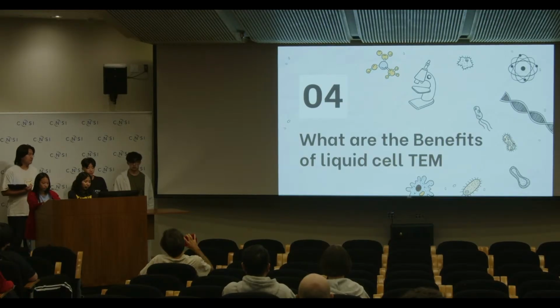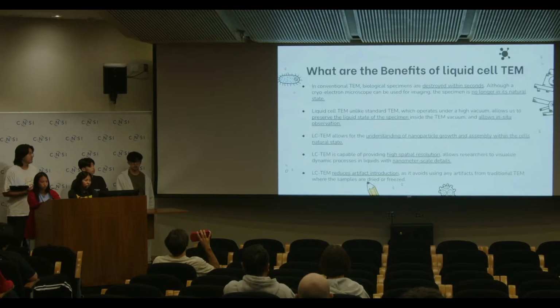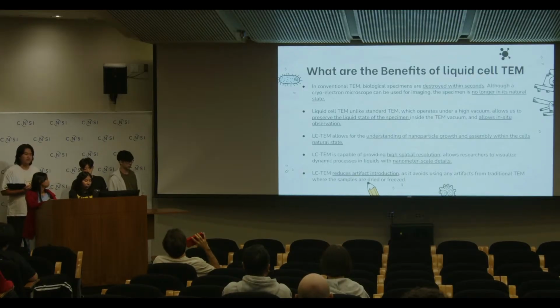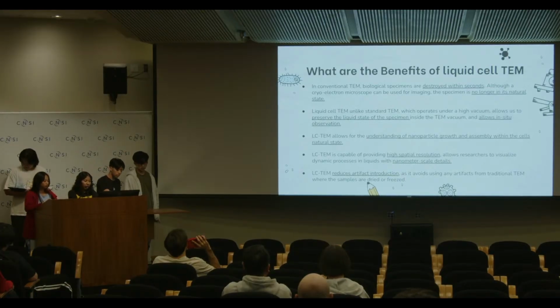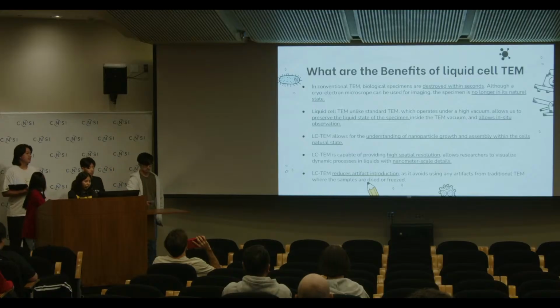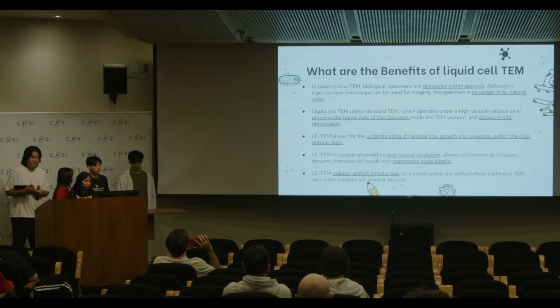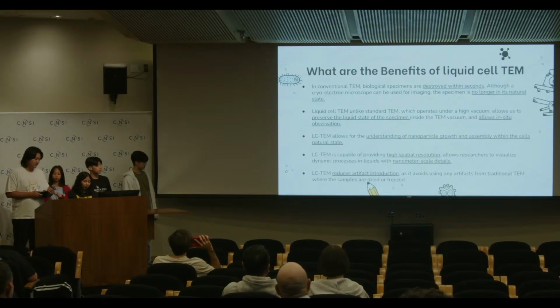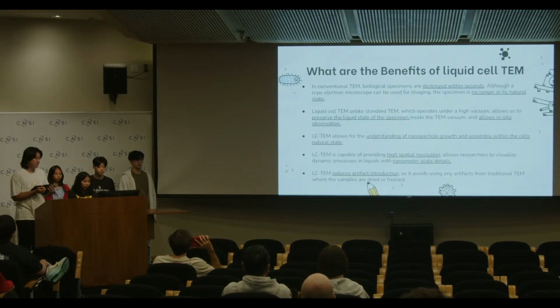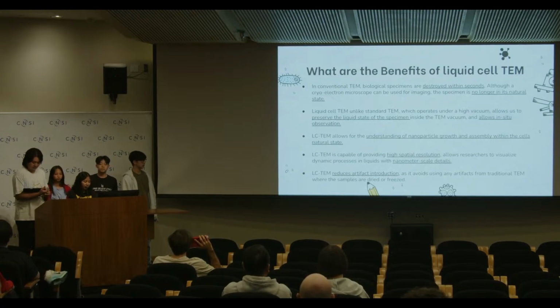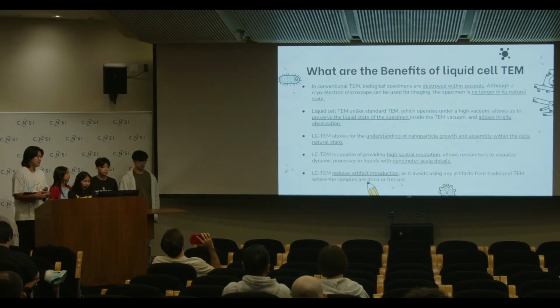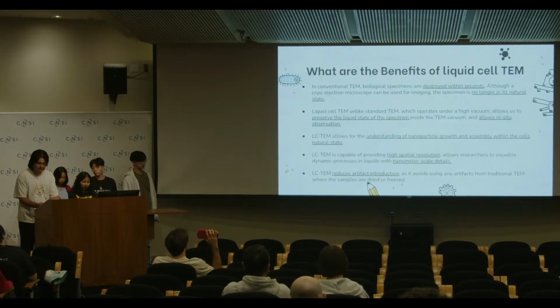Now I'll be going over what the benefits of liquid cell TEM are. To start, in comparison to conventional TEM or also cryo-EM, we are able to use liquid cell TEM to preserve the liquid state of the specimen inside a TEM vacuum, and it allows for in situ observation. LCTEM, or liquid cell TEM, allows us to understand the nanoparticle growth and assembly within the cell's natural state. We're able to use LCTEM for providing high spatial resolution images, which are helpful when allowing researchers to visualize dynamics and processes in liquids with nanometer scale details.